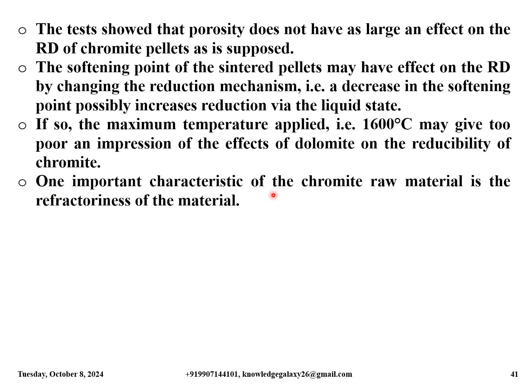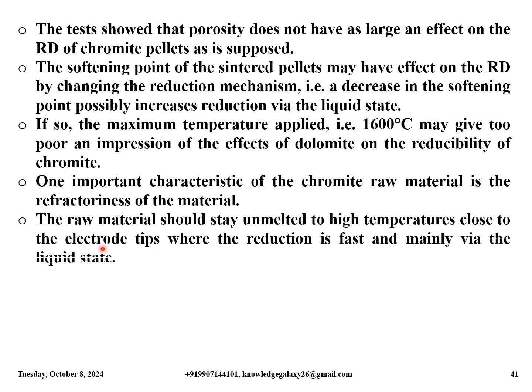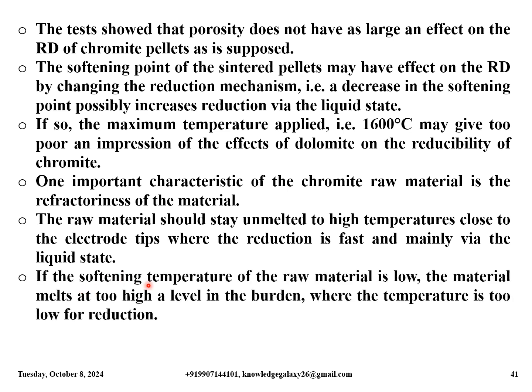One important characteristic of the chromite raw material is the refractoriness of the material. The raw material should stay unmelted to high temperatures close to the electrode tips, where the reduction is fast and mainly via the liquid state. If the softening temperature of the raw material is low, the material melts at too high a level in the burden, where the temperature is too low for reduction.